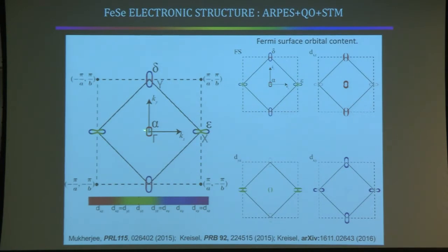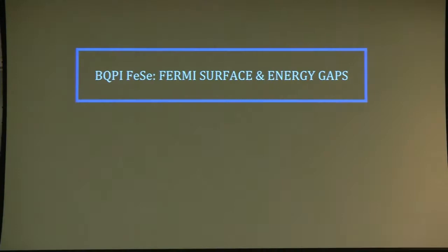Here's the Fermi surface. Here's the first Brillouin zone. This pocket near the center of the Fermi surface is dominated by two orbitals, dxz and dyz. This pocket is dominated by dyz and dxy, and this pocket is dominated by dxy orbitals in this model. So we could segregate the Fermi surface into where the spectral weight is coming from different orbitals. We're using that piece of information to motivate what we're doing.